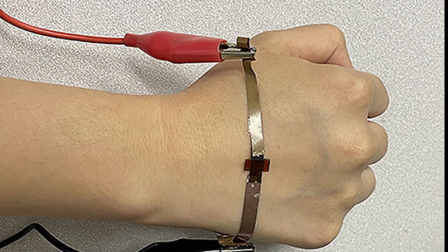This pulse reading could be combined with an electrocardiogram reading to yield blood pressure measurements without a cuff. In the second design, the researchers incorporated nanoparticles of molybdenum disulfide — a semiconductor that can act as both a conductor and an insulator — into the LIG foam. These nanoparticles enhanced the foam's sensitivity and resistance to physical forces, and the design proved resilient to repeated use, showing nearly identical performance before and after nearly 10,000 uses.